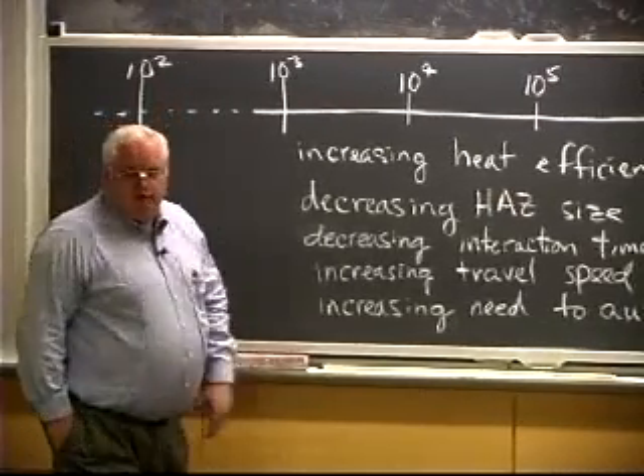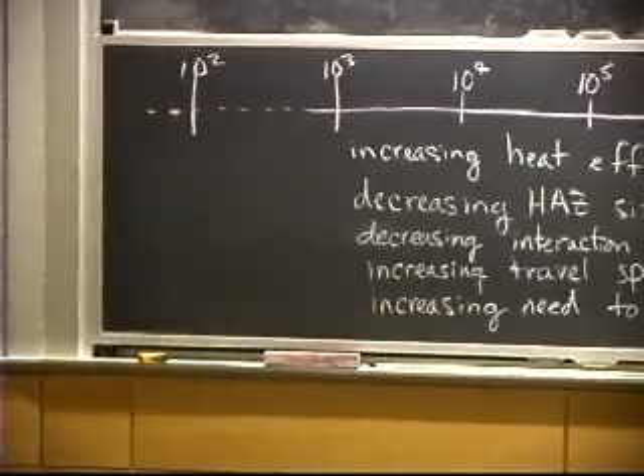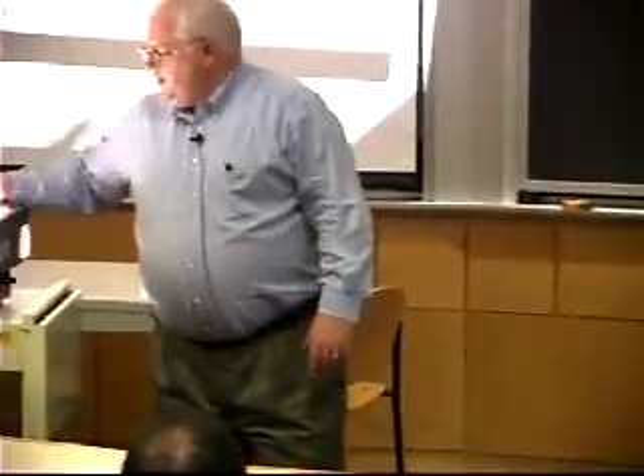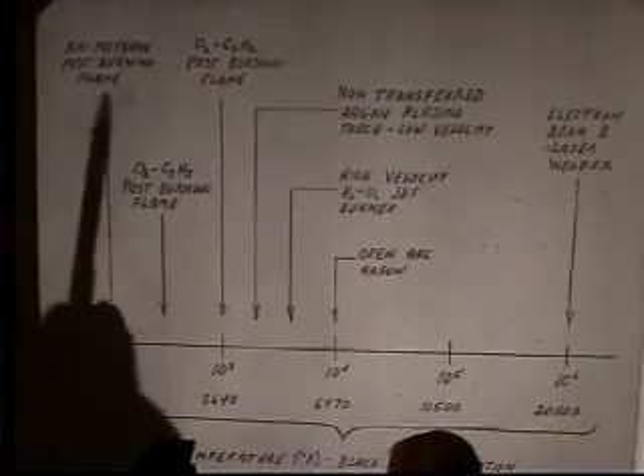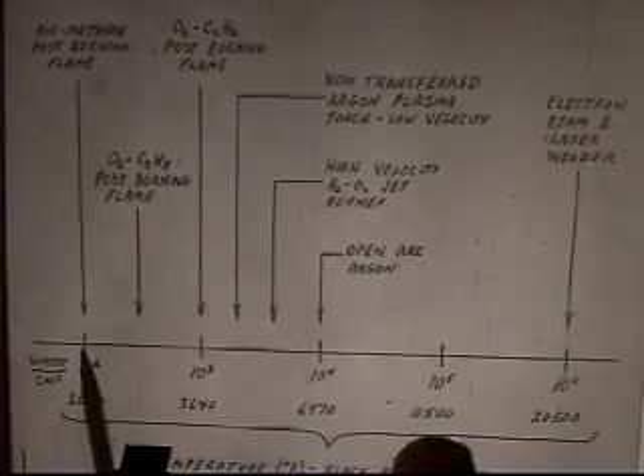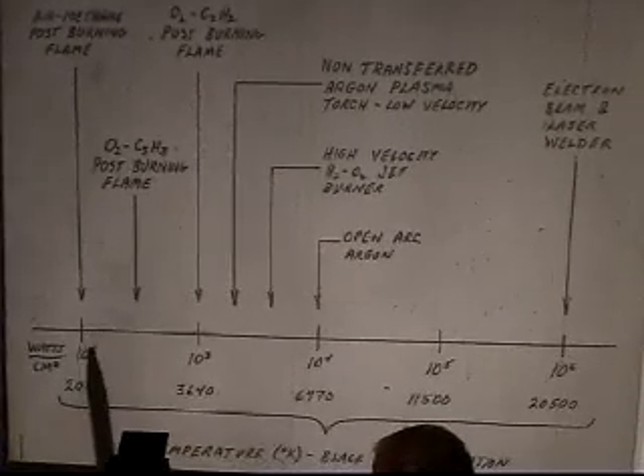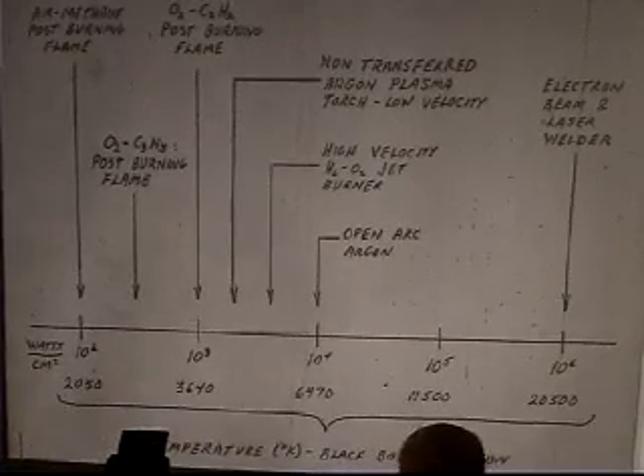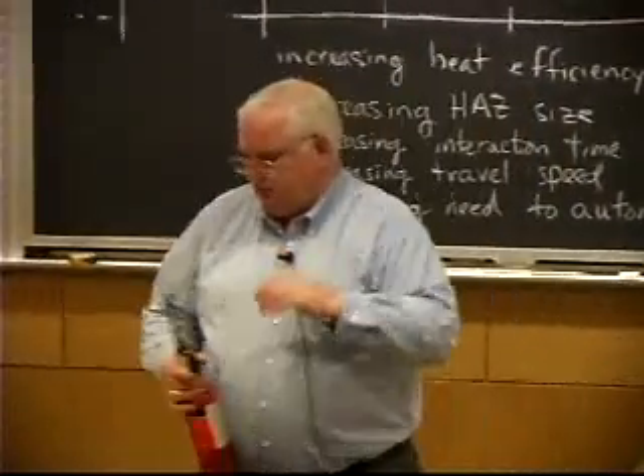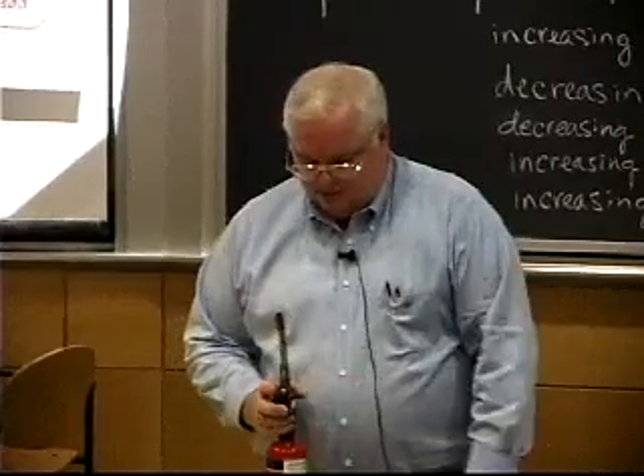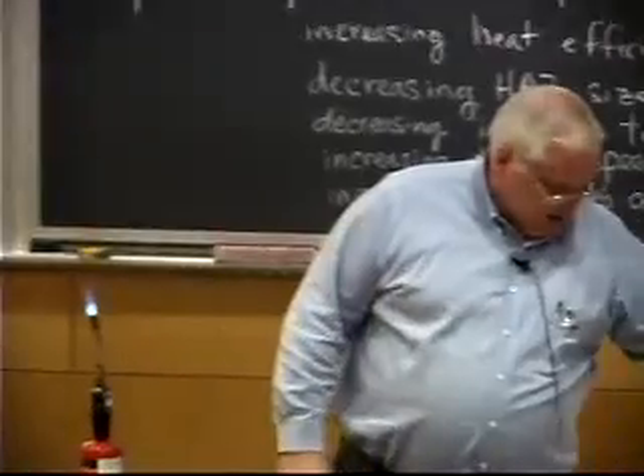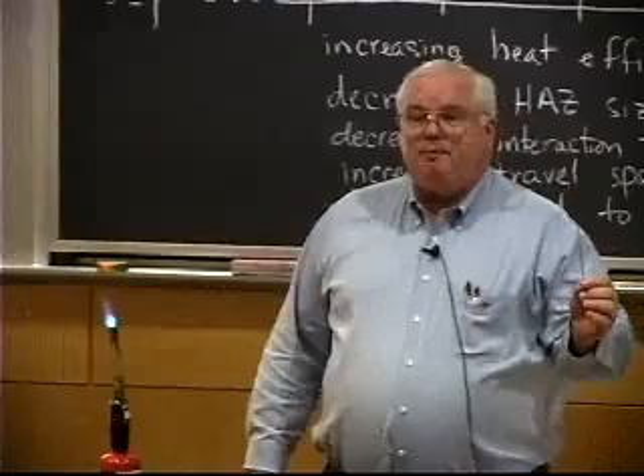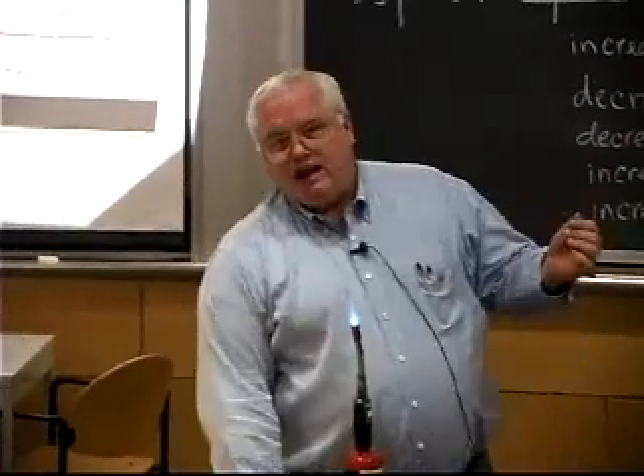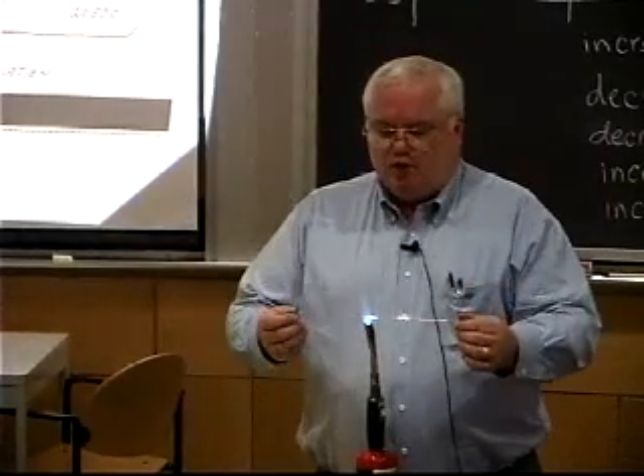And I can show that to you very quickly here. I'll do another demonstration probably next week. But if I look at something that's an air methane flame, that would be basically something like a Bunsen burner or a propane torch. And that will give me about 100 watts per square centimeter. So I just happen to have a propane torch. And I have a piece of steel, nice small piece of steel, so that if I can melt it, it will melt. I put it right in the middle of the flame,